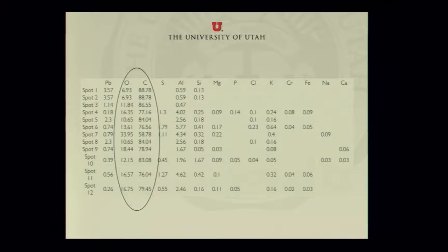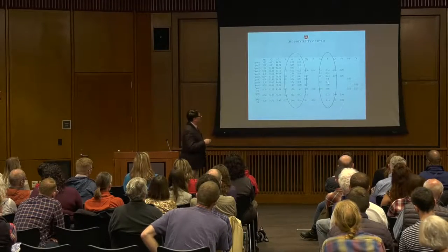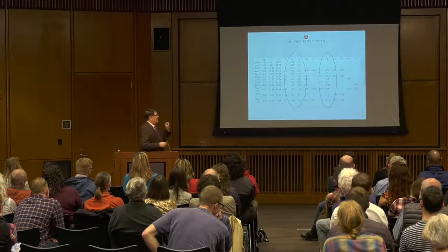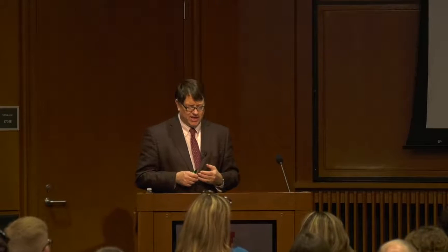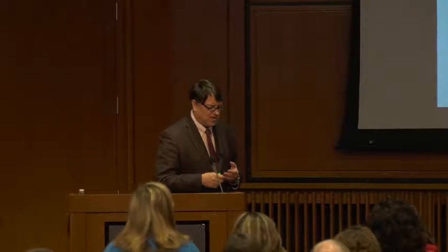We also see a lot of oxygen and carbon in this particular pigment, as well as aluminum, potassium, and silicon all correlated with one another. To make a long story short, these elements suggest that this pigment may have been what's called a lake pigment. The term 'lake' comes from lacquer — lacquer often has a reddish color, and that's where the term comes from. Our speculation was that this pigment was a synthetic pigment — that the Egyptians actually figured out how to make a synthetic purple pigment.